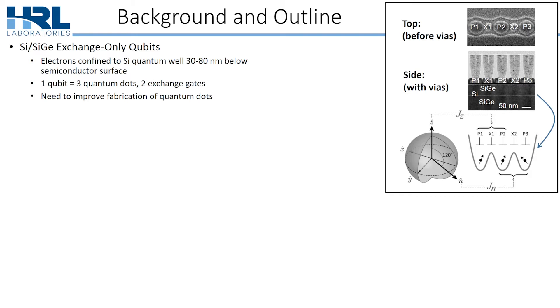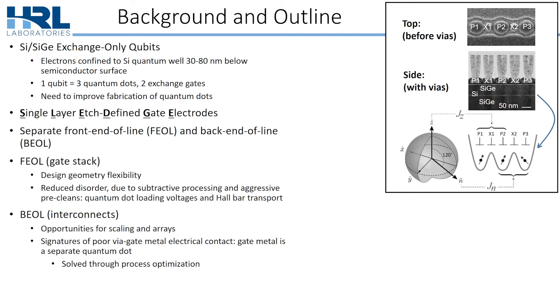We need more quantum dots for every qubit. So the challenge is we need to get good at fabricating quantum dots. Our solution was what we termed SLEDGE, which stands for single-layer etched-defined gate electrodes. We can finally design whatever front-end-of-line surface gate geometry we want and use the back-end-of-line to connect it to the outside world in a different step. The benefits include reduced disorder because the subtractive front-end allows for aggressive cleans before gate stack.